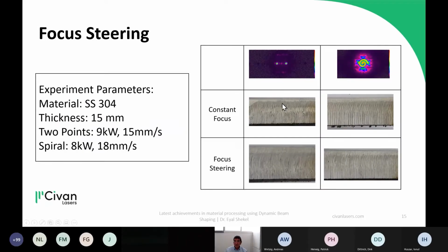And here we see some results. So in the chart, you see on the left a cross-section of one shape, and on the right you see a cross-section of a different shape of a spiral, where the top line is with a fixed focus and the bottom line is with focus steering. And of course, just like was just presented in the previous presentation, you get a much smoother cross-section and no dross at the bottom when you actually do the focus steering. But with our laser compared to a Galvo, it can be done at any power, at any speed, and very high reliability. So it opens up a whole new set of options.